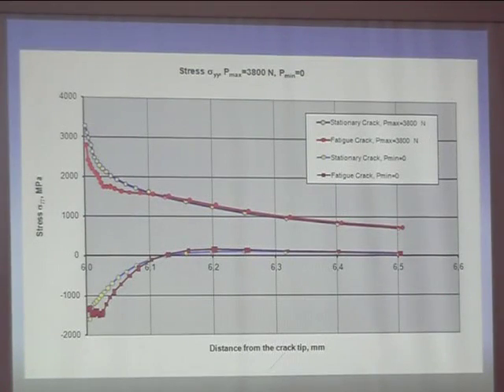Okay, so then we went ahead of the crack with stresses. Here we see the stress distribution, the stress component normal to the potential crack plane. This is what we call the virgin crack, the blue one without history. This is maximum load, this is minimum load. And here we see the stresses of the fatigue crack. This is at 0 load, and this is at maximum load. So when we take that region close here, we see very clearly that the minimum didn't change too much, but the maximum changed. So the stress range has changed ahead of the crack tip, and probably the strain range also has changed.